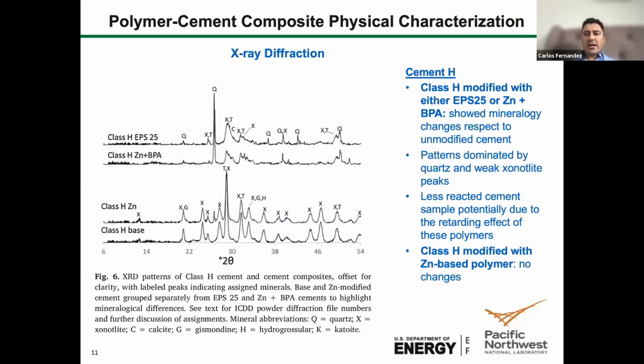X-ray diffraction, we did analysis. We took 2 kinds of polymers, 2 types of cement, H and also the thermal shock resistant cement that is in the next slide. For cement H, after 24 hours, we see that there are some changes in the patterns compared to the cement without any polymer. For a polymer that is polyethylene co-acrylic acid zinc salt, there are no changes. This polymer actually doesn't act as well as a retarder as the other 2, the thermoset epoxy and the BPA combined with the zinc salt. I will not be able to tell you what BPA is yet.